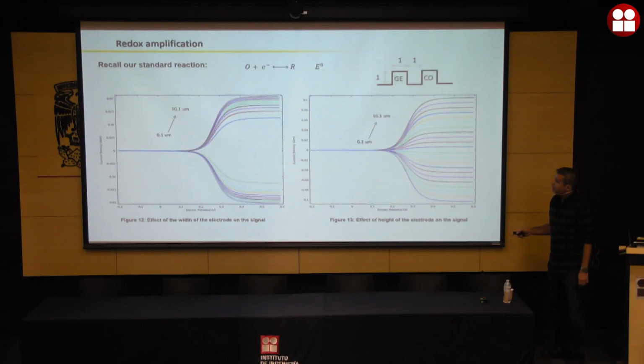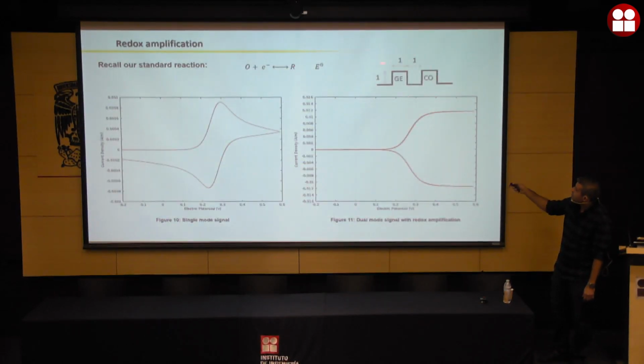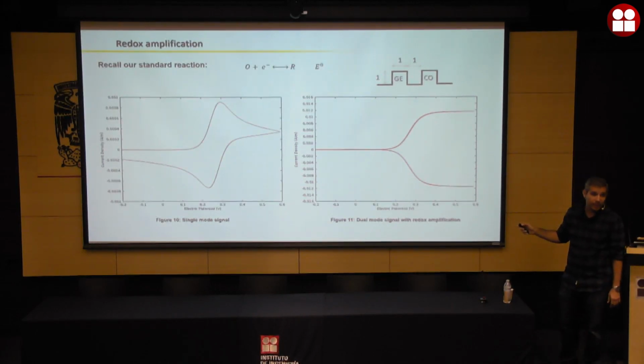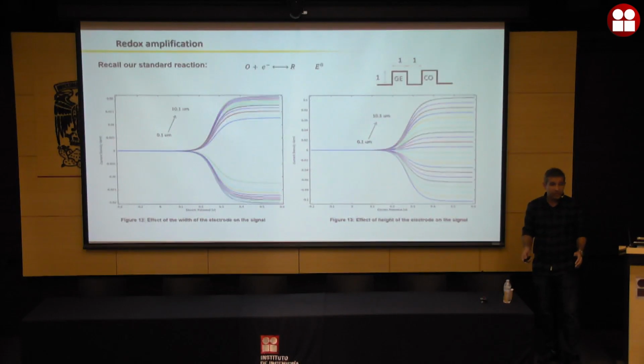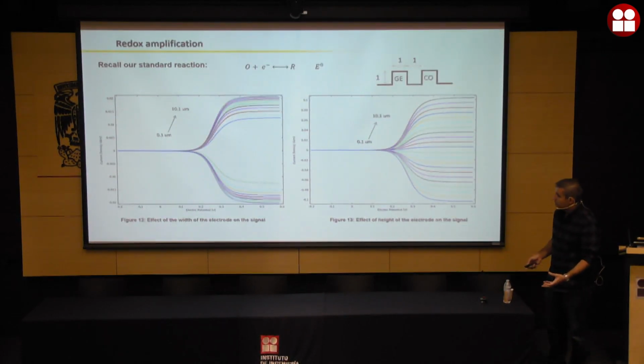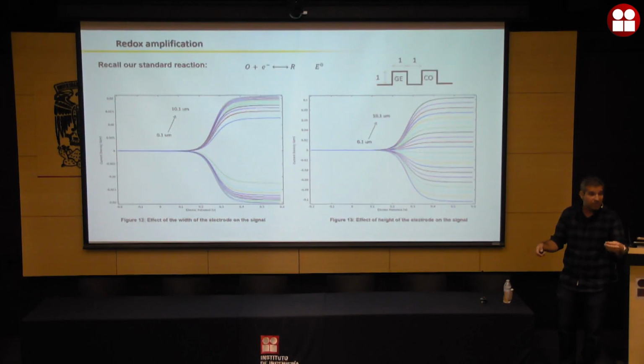Now, the interesting part about this thing is that when you're looking at these IDAs, interdigitated electrode arrays, there are 3 parameters that you can manipulate. There is the width, there is the gap, there is the height of these electrodes. We change all of these variables and try to see what is the effect of each of those variables, right? For instance, we change the width of the electrode from 0.1 micron, 100 nanometer, to 10.1 micron. And you see that this is not linear, but kind of like saturating at 10.1. And this makes sense because if it is at 10.1, I'm almost getting to a macro electrode. And this is like a common sense for an electrochemist, of course. If you have a higher surface area, because electron exchange are surface properties, surface phenomena. If you have a higher surface area, you're naturally going to have higher current density.